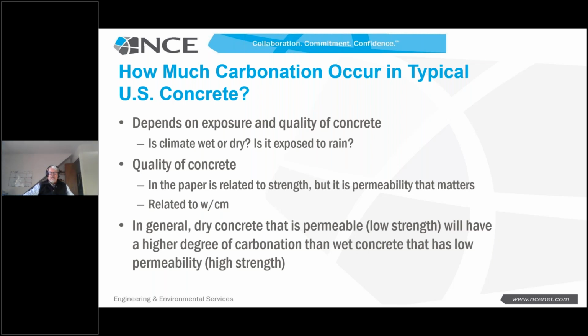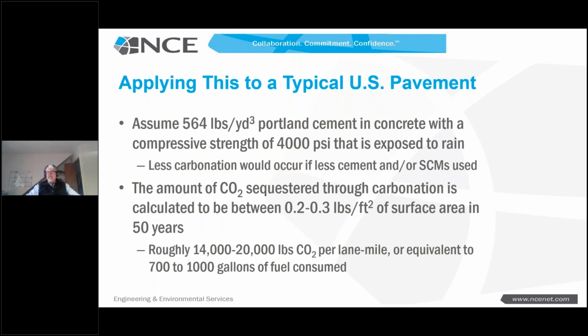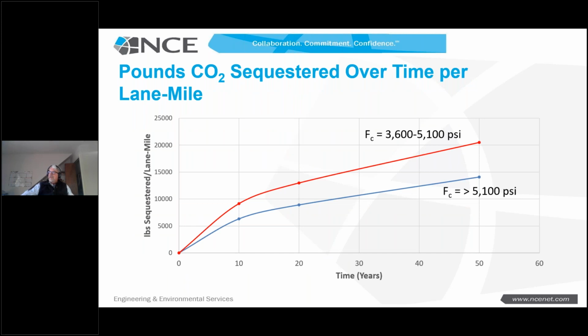If on the other hand, we have very high quality concrete that's underground, concrete that's kept wet, you're going to see relatively low carbonation. And I'm going to do a little illustration here on just a typical US pavement to demonstrate maybe how this could work in a model and when we think about the life cycle. So basically a standard 4,000 PSI concrete pavement, a 6-sack mix, 564 pounds per cubic yard. If we do the calcs, we're going to find out over something like 50 years, we may see roughly 14,000 to 20,000 pounds of CO2 is carbonated per lane mile of that pavement. That's about 700 to 1,000 gallons of fuel consumed, which is not a heck of a lot, but it's not nothing. And it would look something like this with the higher quality concrete carbonating less than a lower quality concrete.